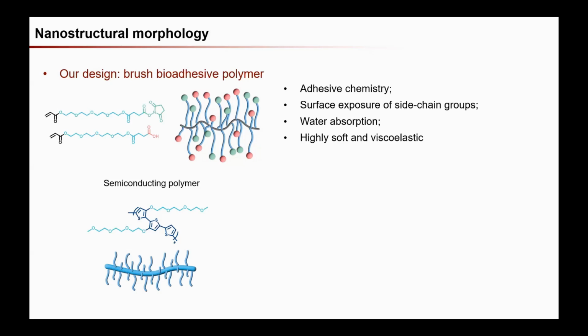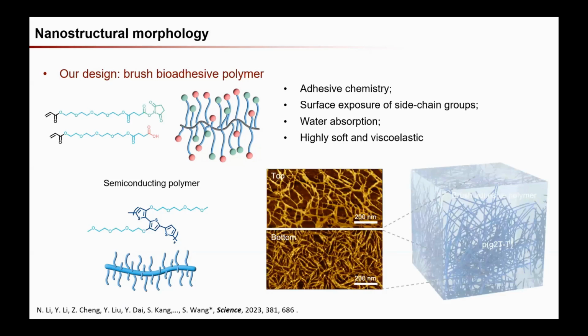So this gives a competition over which side chain end gets to be exposed on the surface. If this side chain is not long enough, you can imagine it could get shielded by the longer side chain. So to win this competition, we had to extend the length of this side chain to be even longer. That's what gives this brush architecture. This design also gives a water absorption property because of the hydrophilic nature. So on the wet tissue surface, physiological biological fluid can be temporarily removed by absorption into this polymer, similarly to a piece of sponge. The surface can be temporarily dried, and it also has the desirable mechanical property.